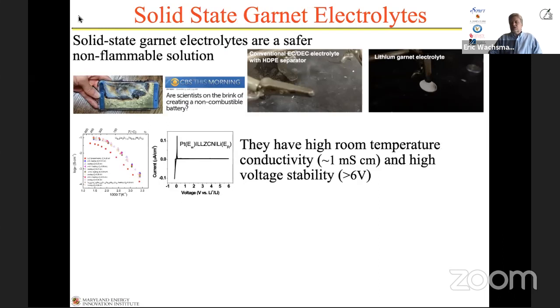The other aspect of these materials, which is quite good, is that they have a high conductivity, that's the plot to the left, comparable to some of the organic electrolytes, on the order of about 1 millisiemens per centimeter. They also have very high voltage stability. That's the plot to the right, going from about 0 volts relative to lithium metal, and I'll come back to why the lithium metal aspect matters, to well over 6 volts. So as far as the range of cathode materials or battery configurations known in the world, this particular material is thermodynamically stable in contact with it, and again has conductivity comparable to some of the conventional electrolytes.